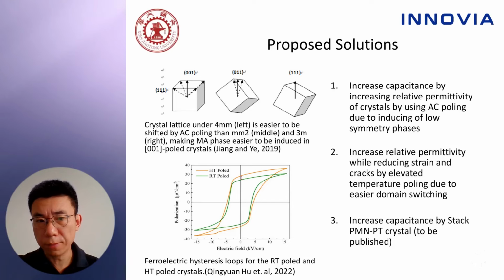Secondly, we propose increasing relative permittivity while reducing strain and cracks by elevated temperature poling due to easier domain switching. The graph on the lower left shows the comparison between crystals poled at elevated temperature versus poled at room temperature. The green curves of the hysteresis correspond to the ones poled at elevated temperatures. It has higher remnant polarization and higher energy stored in each curve.